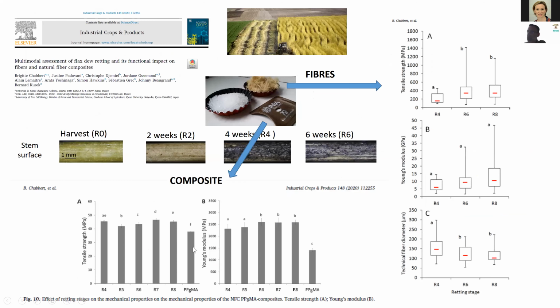So I come now finally to the example. It's sure that we have an effect, even a long-range effect. Even if this effect is not so strong, it is real. If you consider just the fiber at different steps of the retting, you see the color change during the retting from quite green to gray. We have performed all the chemical analysis and determination of mechanical properties of the fiber. You see that when you have the retting step, this is quite overretted. This is a good retting, 6 weeks, at this stage here. And this stage is this one.